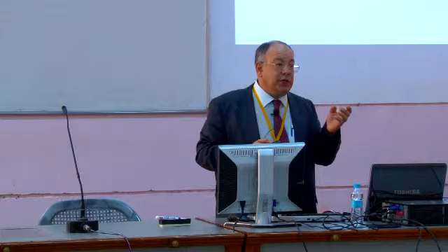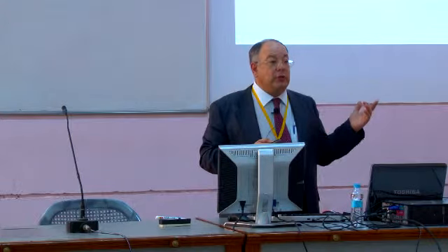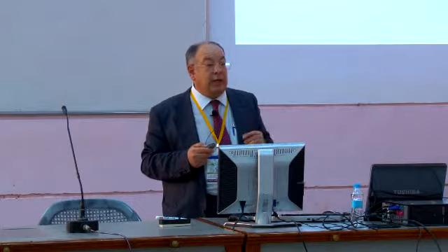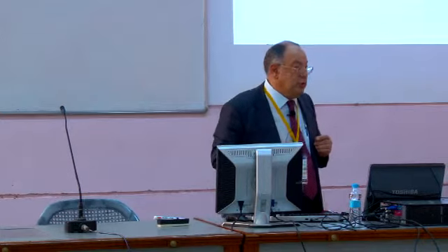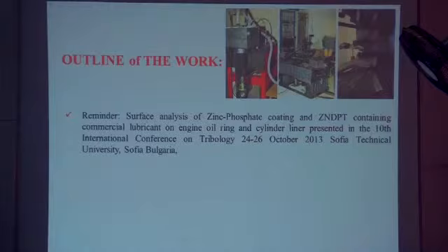As there is zinc and phosphate in the oil, this zinc and phosphate is also removed from the surface and contaminates the oil. This can be very dangerous, because there is a specific composition in the fully formulated lubricant. If you add more additives to the oil, it can be dangerous—it can be positive, but mostly there is an antagonistic effect, not a synergetic one, which degrades the lubricant. So we caught this, and we are talking with some piston ring companies about it.